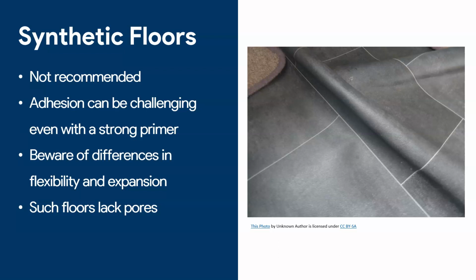These are synthetic surfaces. They've been coated with various plasticizers. It's very difficult to get epoxy to stick long term on it. You may get it to stick for 1 week, and then it will start peeling. Another big problem is that you've got these problems with flexibility and expansion. Look at these materials, they are very flexible. Epoxy is not like that. So for any reason this material starts to move, the epoxy will simply crack.